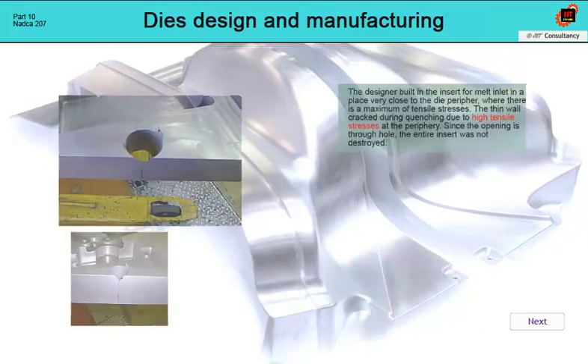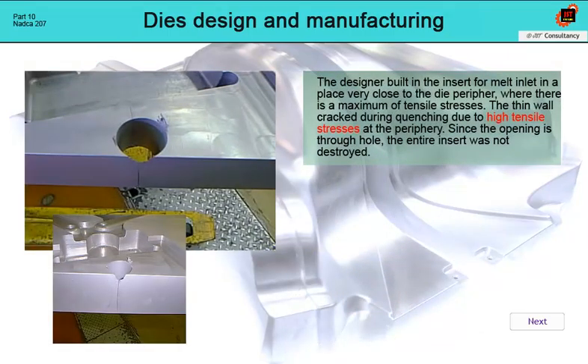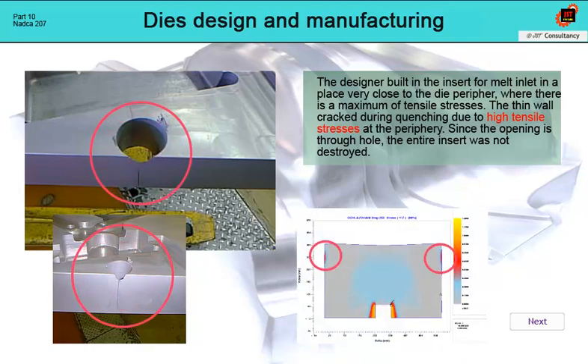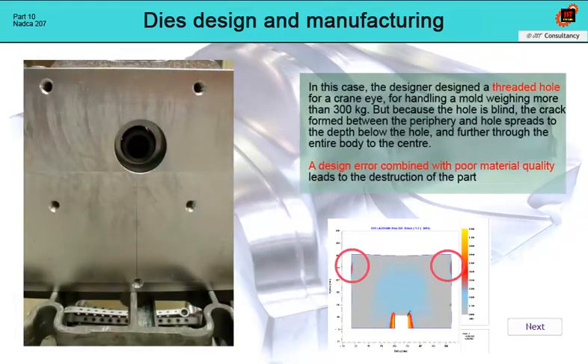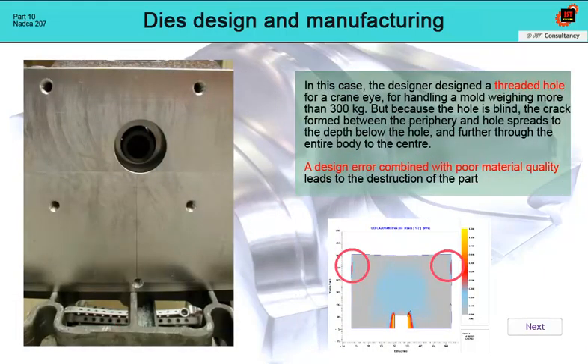In this example, it can be seen that the maximum tensile stresses during hardening occur not in the center of the die, but at its periphery. In this case, the designer built in the inlet gate close to the periphery. The thin wall bridge of the material was torn during hardening due to tensile stresses. Only because the hole was through did the crack cause no further damage. Otherwise, the entire die, weighing more than 300 kilograms, would probably be destroyed. In this case, the designer was not so lucky. As this was a heavy piece, a crane eye hole had to be added to the back side.